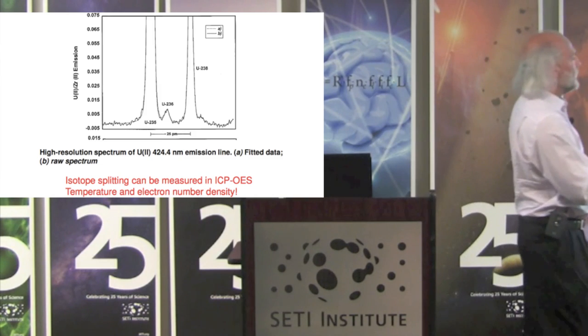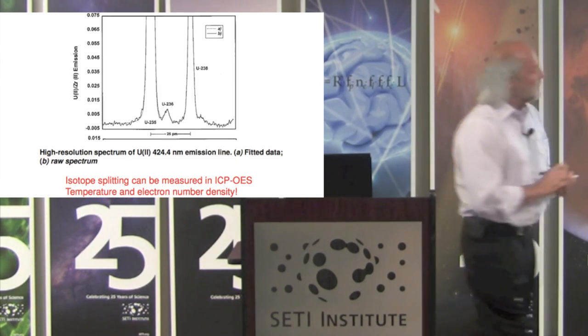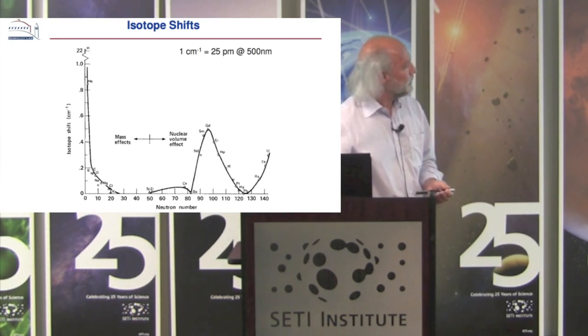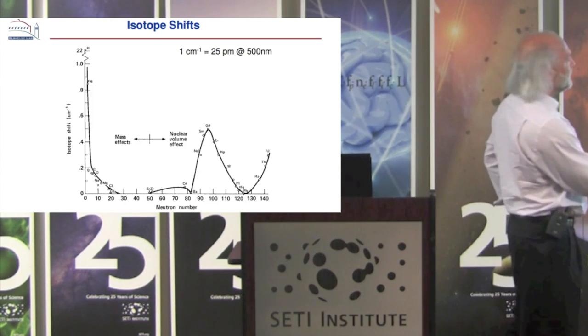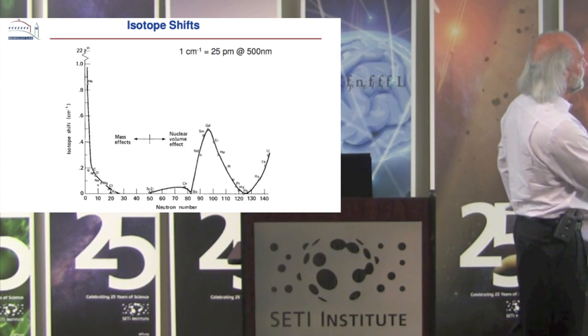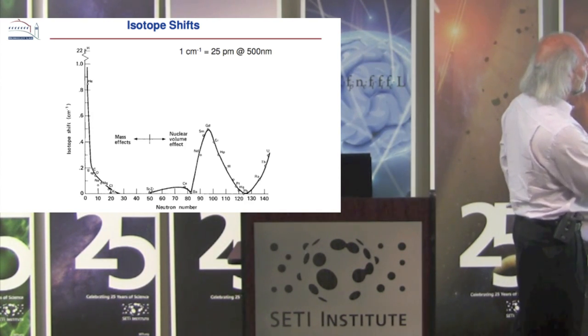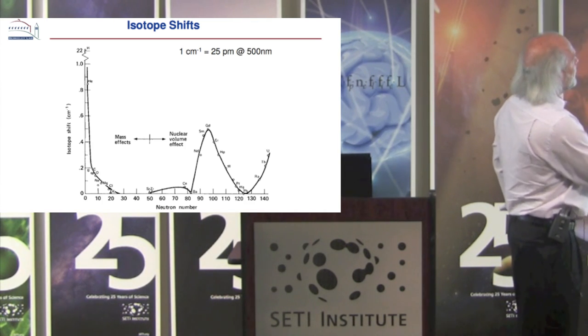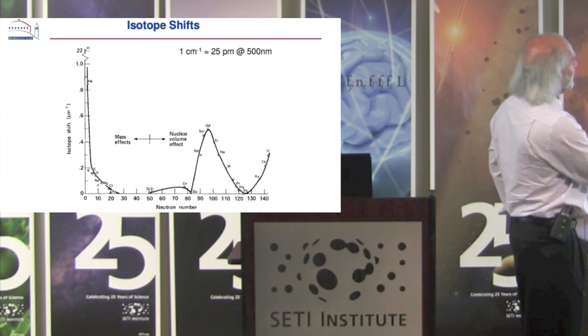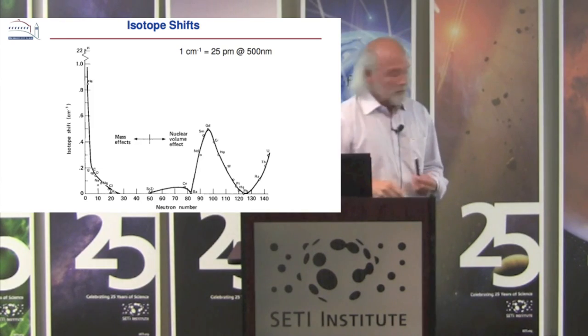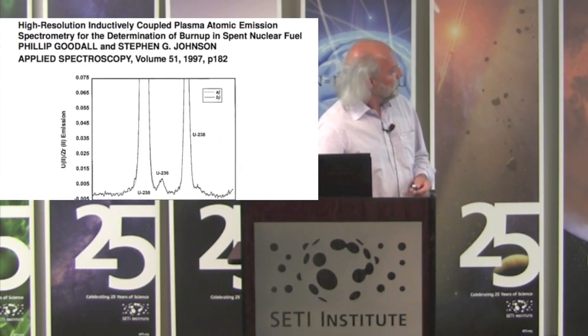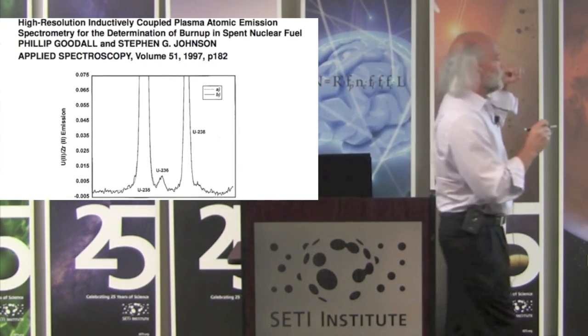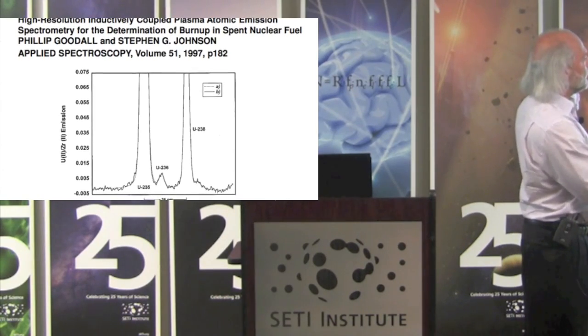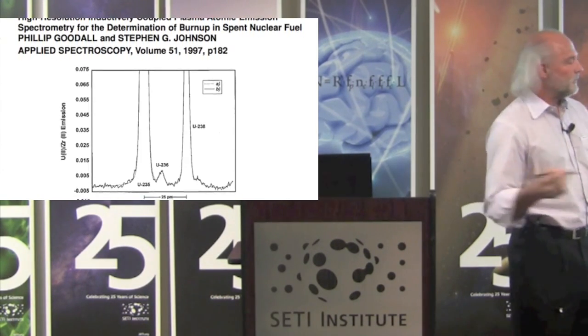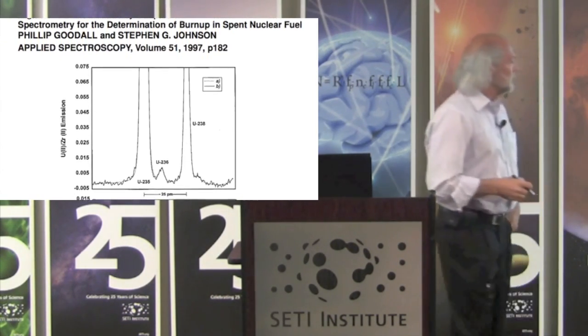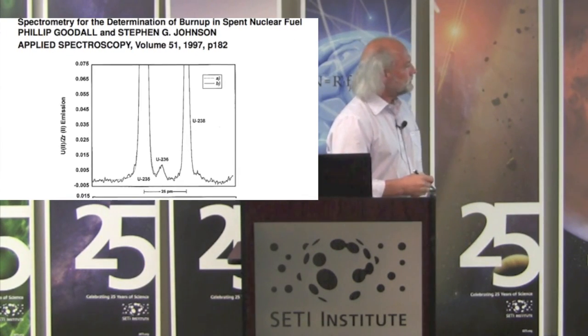And this is actually one of the largest shifts, especially for a heavy element. If we go back to this slide, uranium's out here. So you can see gadolinium, samarium, some of the rare earths have a little bit bigger, but that's not a big scale. And then obviously helium and some of your lithium and boron will have bigger shifts. But uranium is considered one of the largest isotope shifts for 235, 238, and of course the government's very interested in that for non-proliferation issues.